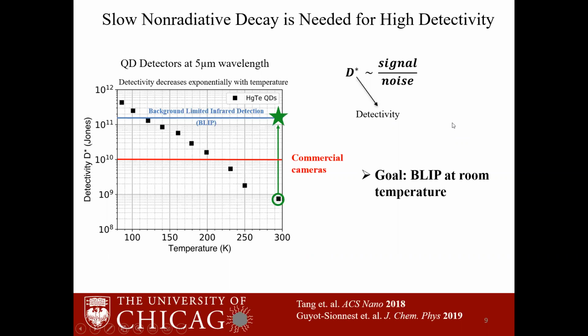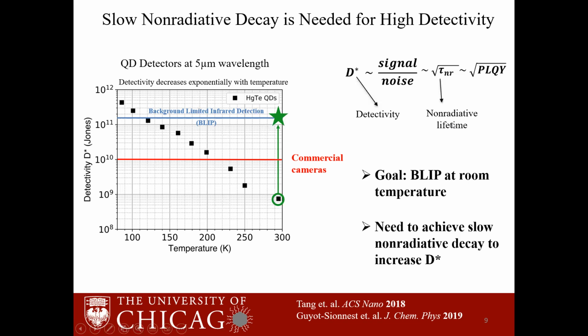The dream is to achieve background limited detection near room temperature. So this exponential trend decrease is because the noise increases at higher temperature due to thermal recombination. So we need some way to reduce this noise without cooling the detectors. And we can do this by slowing the non-radiative rate. So in the next slides, I will talk about what non-radiative relaxation is.